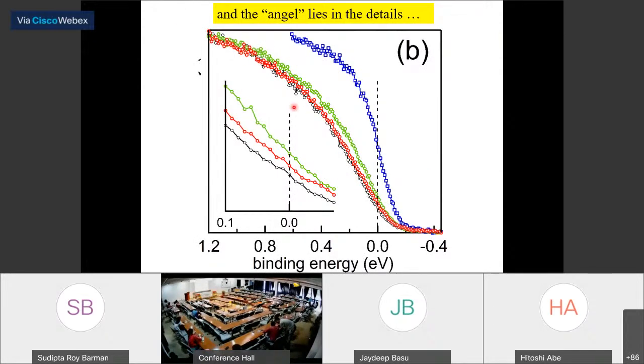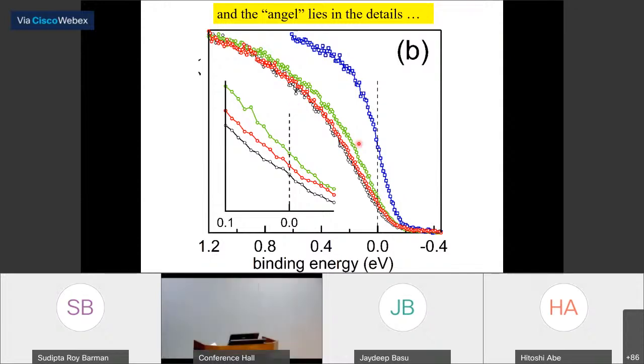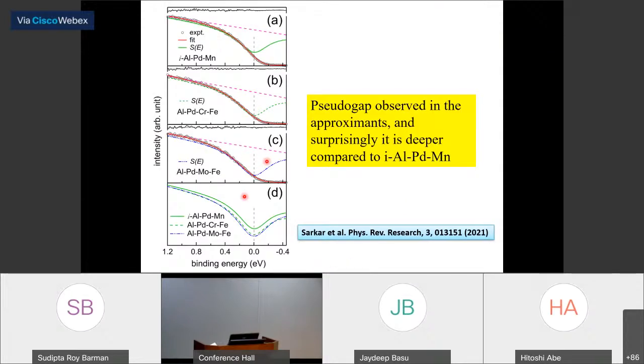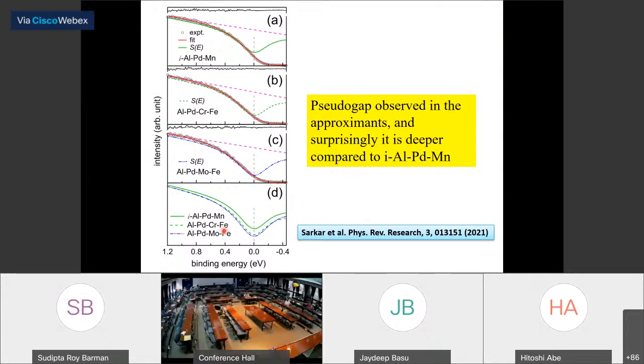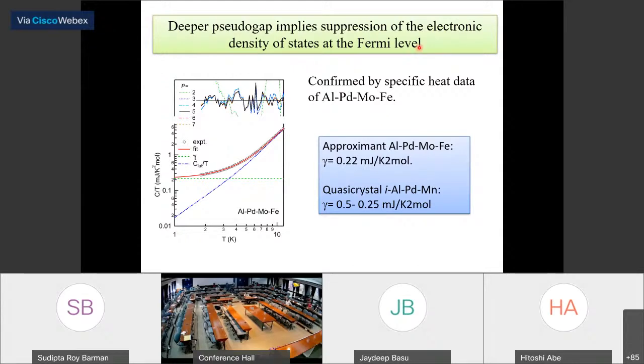If you look at the states close to the Fermi level, you can see there is a clear difference between these three samples. And if we analyze them and find the shape of the pseudo gap, if we close down on this graph here, you can see this is the pseudo gap of AlPdMn, and the AlPdCr and AlPdMo have a deeper pseudo gap, slightly deeper compared even to the AlPdMn. And we tried to also confirm this through real bulk measurements like specific heat, because a deeper pseudo gap implies suppression of the electronic density of states, and that is related to the specific heat, and the specific heat also confirms this.